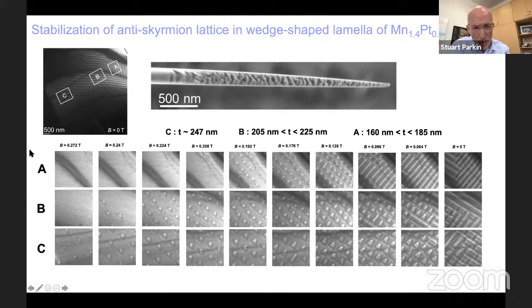And then you can see for these regions A, B, C, these correspond to three distinct thicknesses of the lamella through which we're imaging these chiral structures. And they show you from the left column, it's in 0.27 Tesla, a relatively high magnetic field that stabilizes the magnetization along the tetragonal axis. We're looking along the tetragonal axis. And then it shows you what happens as we reduce the magnetic field. You eventually start to see here at 0.2 Tesla some anti-skyrmions, and then at 0.1 Tesla you start to move into the helical state. And you see at 0 Tesla you can see these two different orientations of these helical structures.